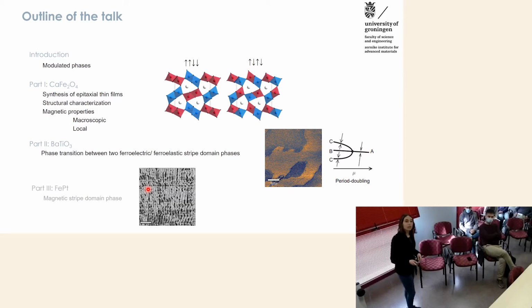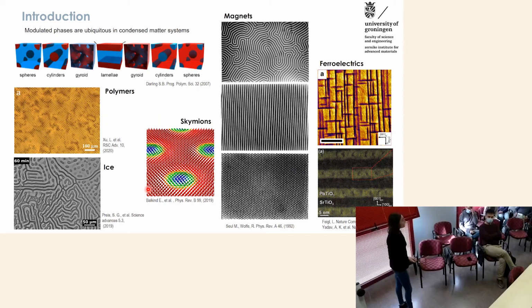As a brief introduction, modulated phases are ubiquitous in nature, and we keep on seeing the same kinds of shapes and patterns all over in systems which are very different from a microscopic point of view, from the interactions that they have, but also on very different length scales. In this slide, you can see block polymers or polymer thin films, solid systems like ice, and again, magnetic systems or ferroelectrics, where you can always see this kind of modulations and patterns at different length scales. This indicates that there is a general mechanism that forms these phases, and the evolution of these phases under different external stimuli like temperature or fields is somewhat similar.